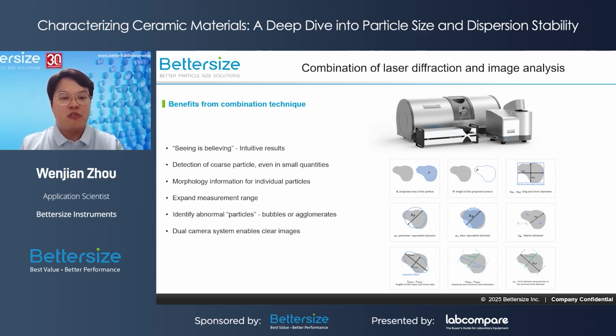Image analysis solves this problem by capturing images of individual particles, including the few large ones, and processing them to generate size and shape parameters. Images do not lie. They provide intuitive results so that we won't miss coarse particles, and up to 24 particle shape parameters can be provided, including circularity, Feret diameter, and aspect ratio.